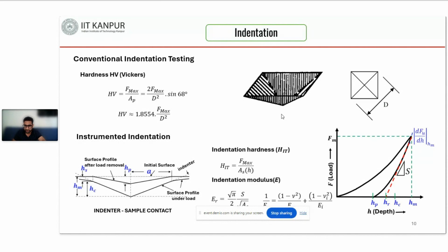After removing the indenter, there is an impression made on the sample surface, and we measure the area of this impression in the optical micrograph and calculate the hardness value. The hardness value is equal to the ratio of the force applied divided by the area of the impression made. If you see the geometry, it's a square shape.